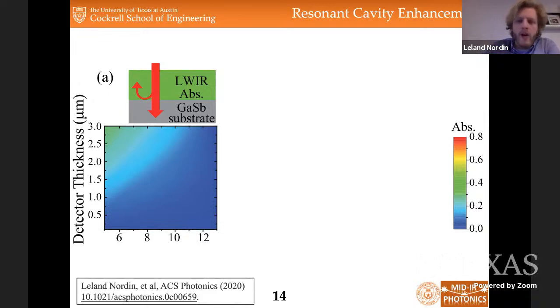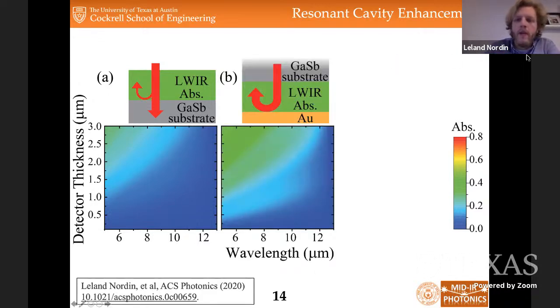This isn't a totally fair comparison, because actually people often metallize one side and then detect through the substrate, and you get a double pass configuration shown here. So you get a little bit of an increase in absorption, but you still need to grow relatively thick absorbers, and generally speaking, your dark current or your noise in your detector scales with your absorber thickness. So even though you're growing thicker and thicker absorbers, you're also incurring more and more dark current.